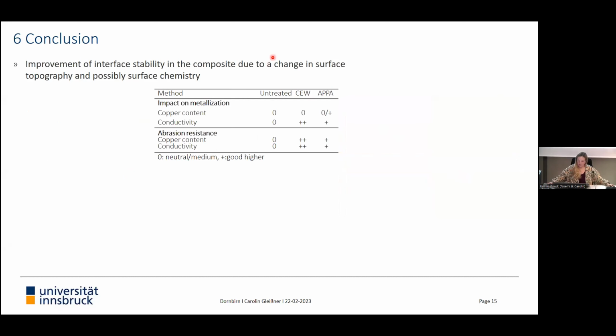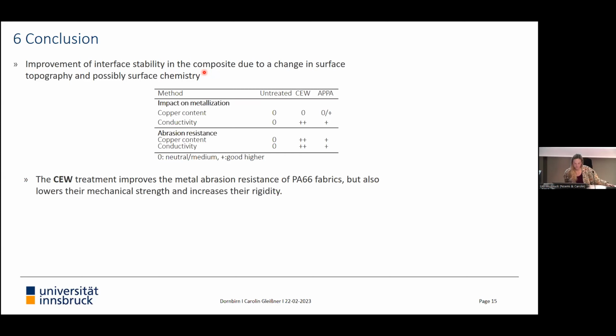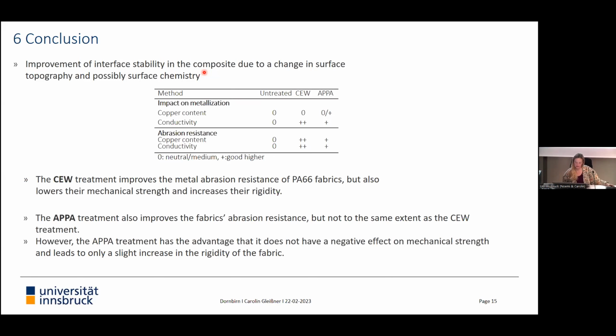To conclude, with the complexation method and also with the plasma method, we could improve the interface stability in the composite due to a change in surface topography and also surface chemistry. The CEW treatment improves the metal abrasion resistance of the fabrics, but we also observed that it lowers its mechanical strength and increases its rigidity.